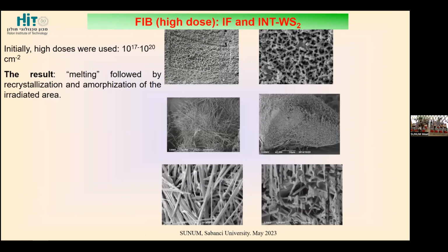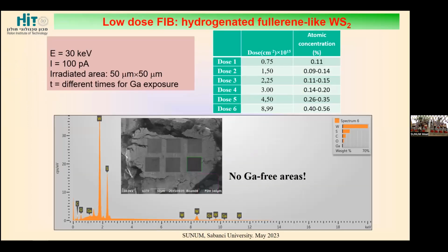The first results were not so good because we tried to use very high ion doses, and there was a lot of amorphization and melting and destruction of the material structure. Then we tried to use lower doses, but for lower doses we did not get any gallium inside, as measured by energy dispersive spectroscopy in SEM. Then, for some reason, we tried to do the same procedure for previously hydrogenated fullerene-like WS2.